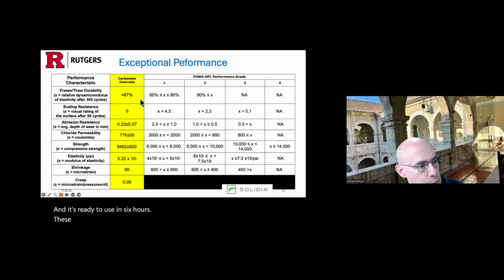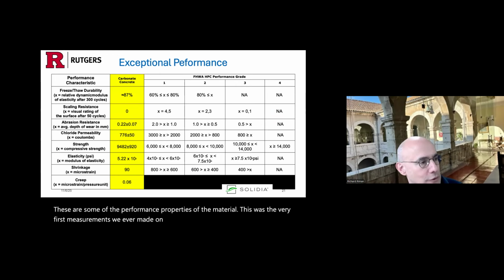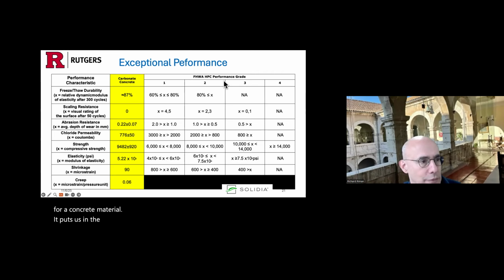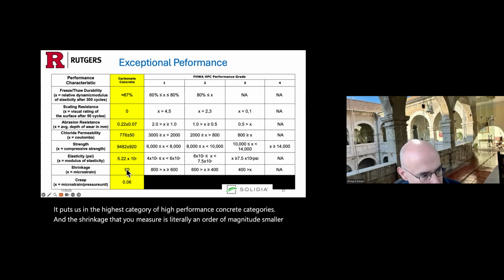These are some of the performance properties of the material. This was the very first measurements we ever made on these materials. And the most important things that you see here is that we've gotten close to 10,000 PSI, which is great for a concrete material. It puts us in the highest category of high performance concrete categories. And the shrinkage that you measure is literally an order of magnitude smaller than anything that you've seen with Portland cement concrete.